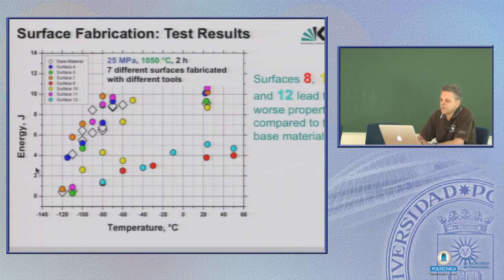And what you can see here, the white points, that's the massive material delivered Eurofer in its initial condition, and all the other ones are with regard to different fabrication routes. So most of them are pretty near or comparable to the base material, to Eurofer, but some colors, red, yellow, and light blue, are worse, or, let's say, really not good compared to the base material.